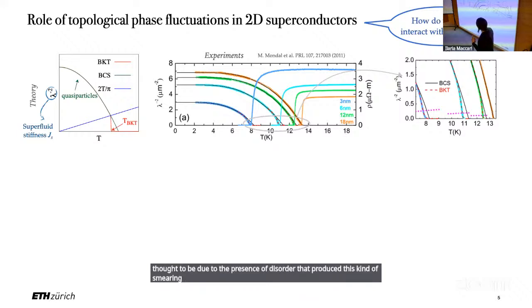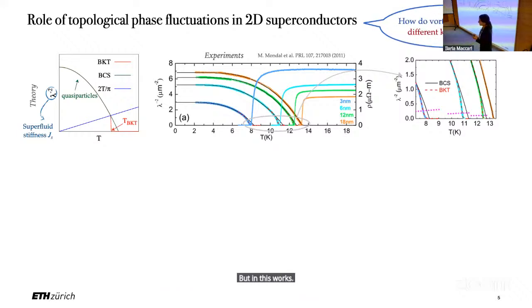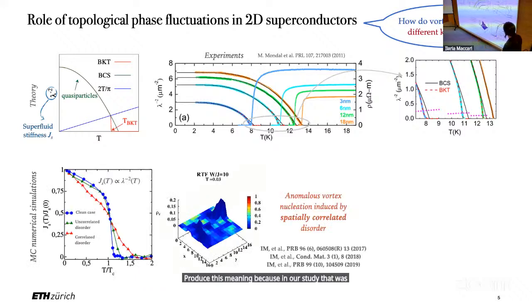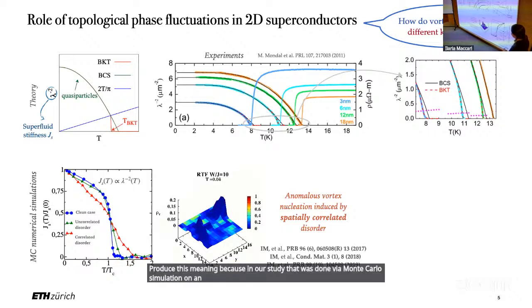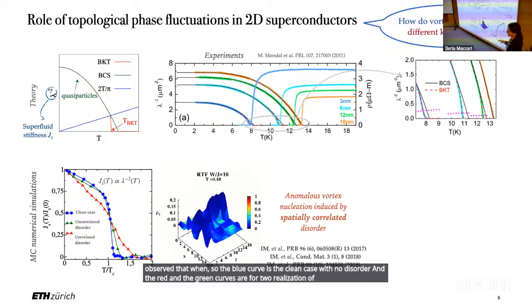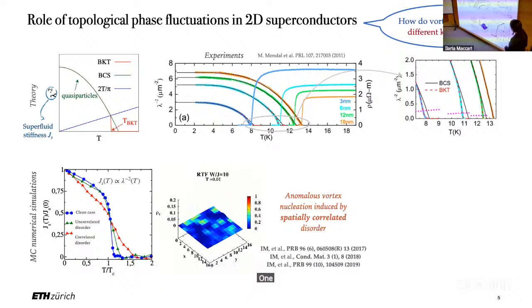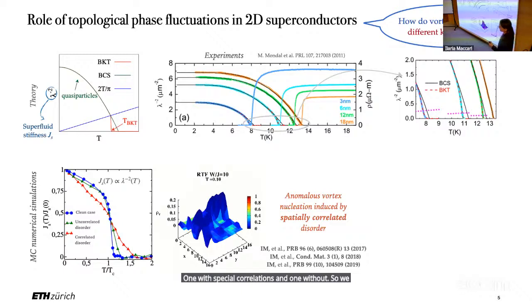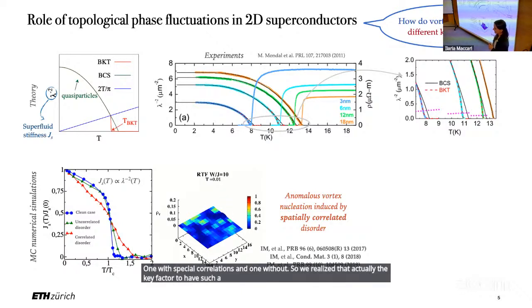But in these works, we realized that the real question to ask was which kind of disorder actually produced this smearing. Because in our study, which was done via Monte Carlo simulation on an effective model for the superconducting phase, we actually observed that, so the blue curve is the clean case with no disorder, and the red and the green curves are for two realizations of disorder with the same strength, one with spatial correlations and one without. So we realized that the key factor to have such a broadening in the transition was the presence of spatial correlations in the disorder.